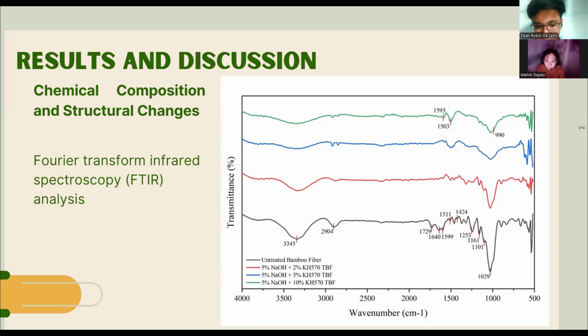The disappearance of peaks at 1511 and 1424 per centimeter, which represent the aromatic skeletal vibrations in lignin, indicates effective lignin removal. This result explains that despite the hydrophilic nature of bamboo fibers, alkali-silane treatment can significantly reduce their moisture retention. The treatment removes hemicellulose and lignin, which are hydrophilic components of the fiber. By removing these, the treatment exposes more cellulose hydroxyl groups, making the fiber surface more reactive, so that when silane reacts with the exposed hydroxyl groups, it introduces hydrophobic groups onto the fiber surface, while reducing the hydrophilic sites that